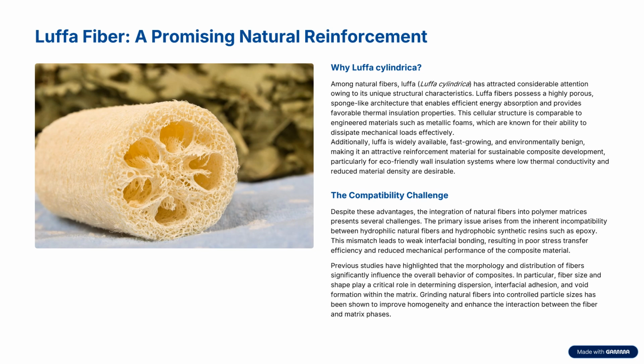Previous studies have highlighted that the morphology and distribution of fiber significantly influence the overall behavior of composites. In particular, fiber size and shape play a critical role in determining dispersion, interfacial adhesion, and void formation within the matrix. Grinding natural fibers into controlled particle size has been shown to improve homogeneity and enhance the interaction between the fiber and matrix phases.